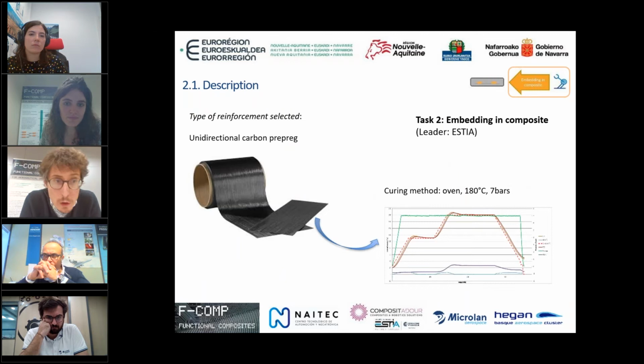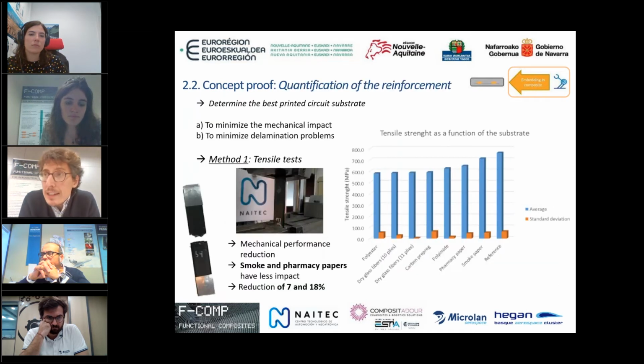First of all was the selection of the material to be used. In this case, it is an unidirectional carbon fiber prepreg, very common in the aeronautical sector, and COMPOSITADOUR is very familiar with it. So for them, it's, let's say, easy now to work with. This material, after doing the stack up, is sent to cure in the oven at 180 degrees with 7 bars at about 2 hours, and then we get the final samples just with the sensor embedded in the composite.